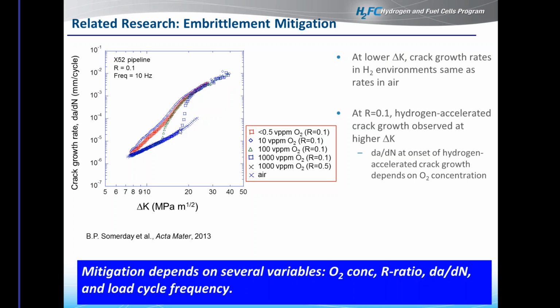And once again, we get accelerated fatigue crack growth rate, which converges with that in pure hydrogen at higher delta K. But really, we're seeing an incremental difference between different amounts of oxygen and when we see the onset of hydrogen accelerated fatigue crack growth. So all these tests that I've shown so far were tested at an R ratio of 0.1. So that would be a more extreme loading ratio. So loads were essentially varied from 10% to 100%.